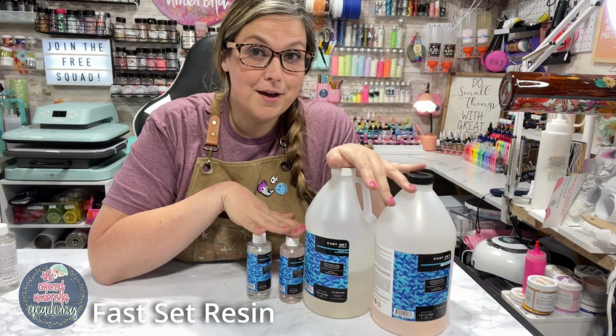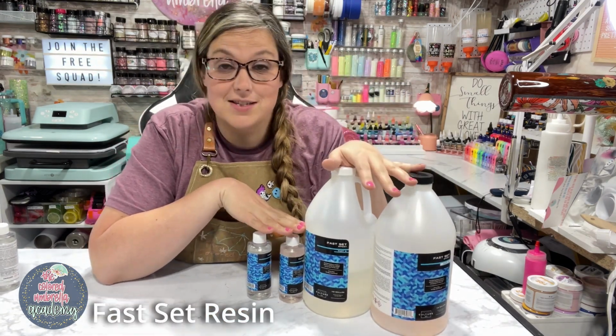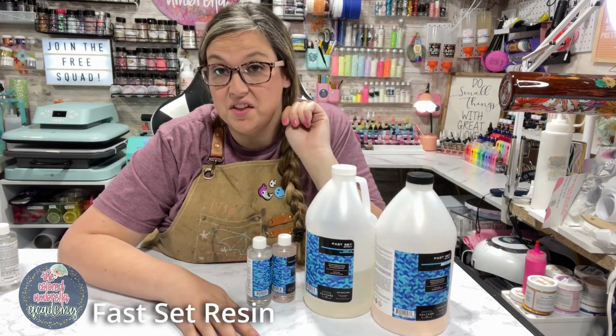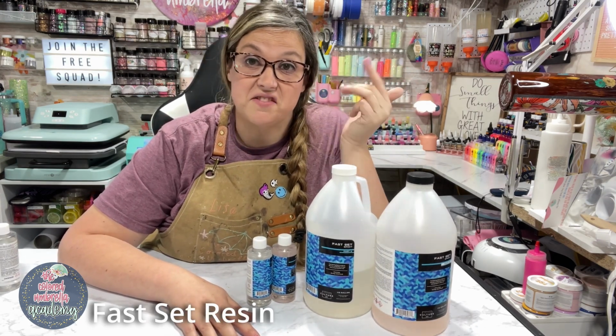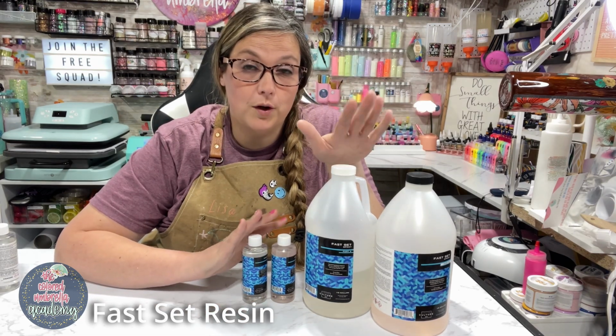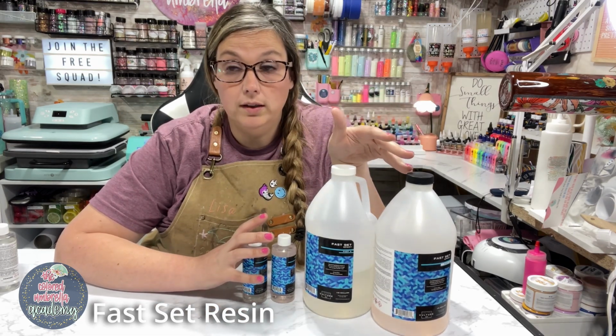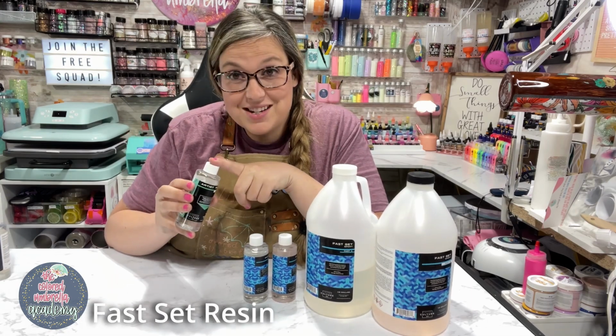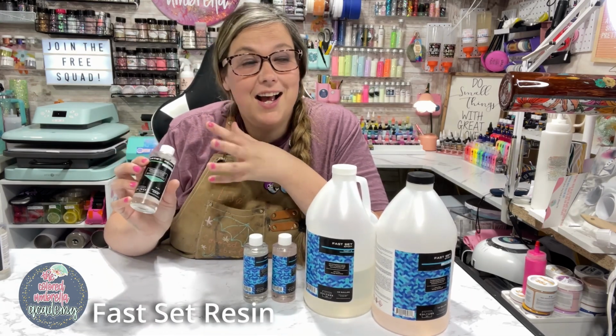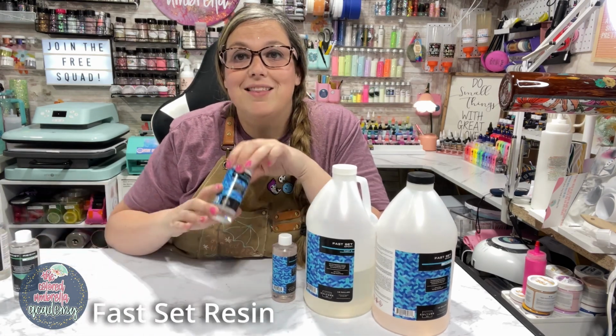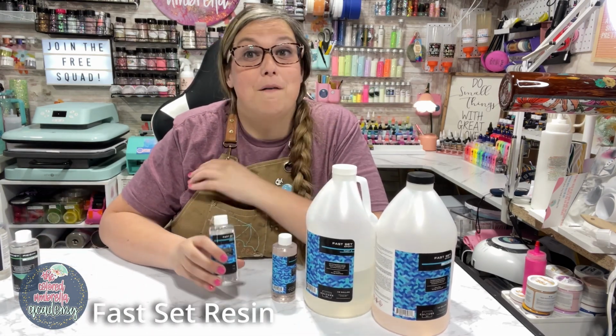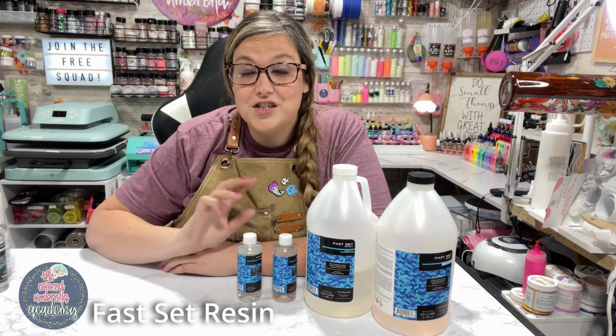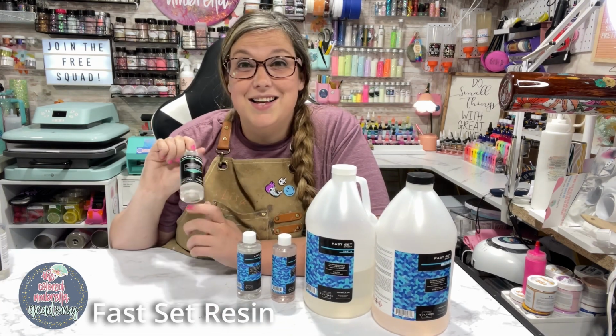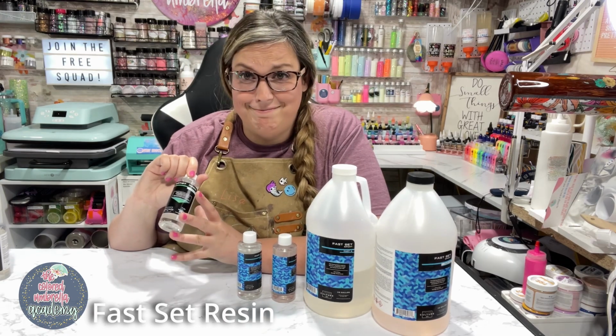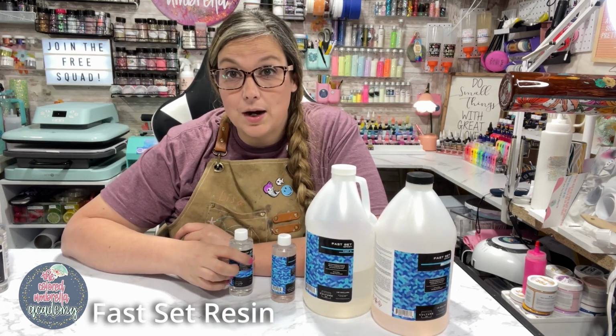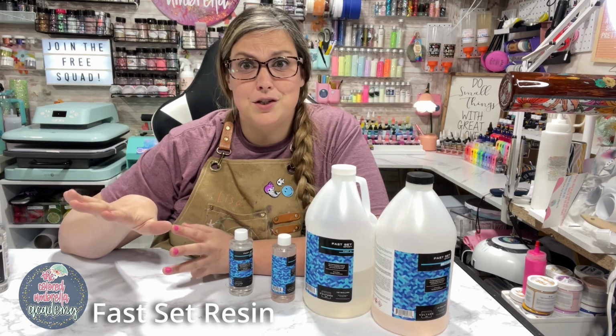Now we're going to talk about my favorite kind of epoxy, fast setting epoxy. What is fast set epoxy? Just like what the name says, it's epoxy that sets fast. Because it sets fast though, your work time is a lot lower. As we talked about with the artist resin and your standard epoxies, you're going to have about 40 minutes of work time. With this epoxy, that drops down to about 15 minutes. Also, this one cures to the touch in 2 hours, as opposed to, I would say, 8 to 10. It is fully cured in 24 hours, as opposed to 48 to 72 hours.